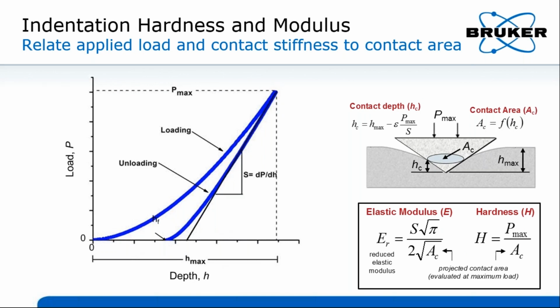Here we introduce the method proposed by Oliver and Pharr in 1992, which is commonly used in nano indentation. There are two key steps in the Oliver and Pharr method for the key value of projected contact area. One is the estimation of contact depth, and the other one is the tip geometry or area function. Assuming sink-in happened at the sample at the contact with the indenter, the method uses the onset tangent of the unloading curve together with a correction factor epsilon to estimate the contact depth hc.